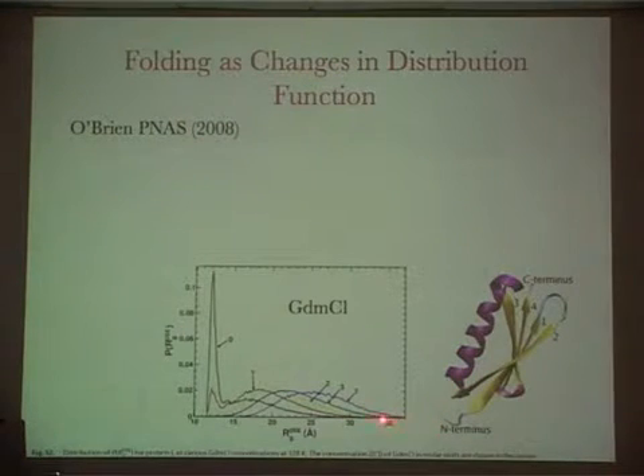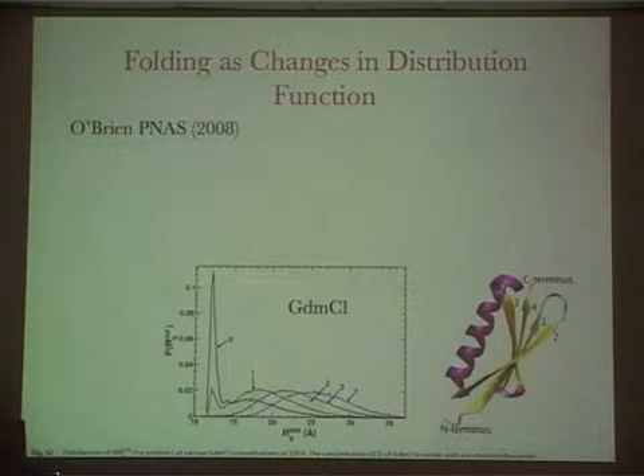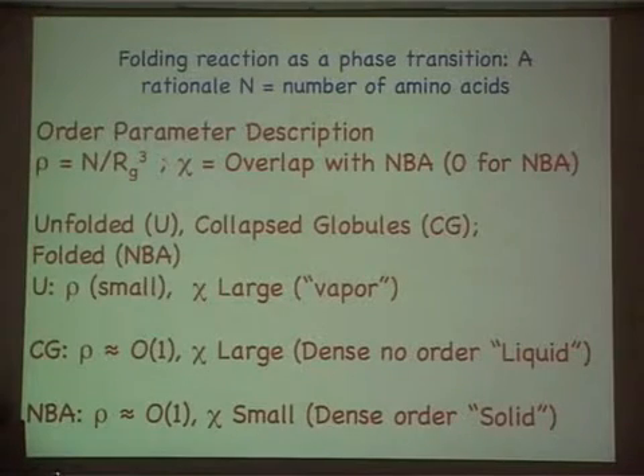And you see that the distribution of radius of gyration changes continuously, in fact, going from high denaturing concentration to 0 denaturing concentration. There is no discontinuity of any sort when you view this folding transition in terms of the changes in the distribution of RG, the radius of gyration. So with that, and with RG sticking in our head, let's think of an order parameter description, if you want, of the folding reaction.